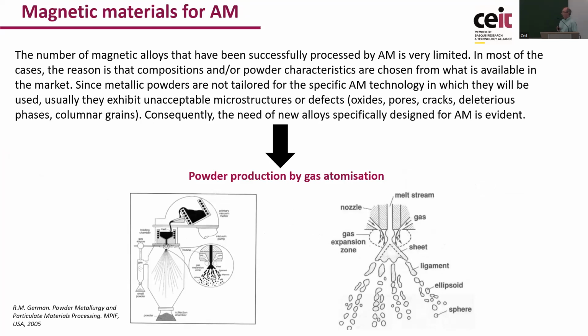The materials are going to be processed by selective laser melting in this project. The characteristics of the powders used in this additive manufacturing technology basically are that they must be spherical to have a good flowability and form a bed with uniform density. The typical particle size range is between 20 and 63 microns. And if possible, they must have a low oxygen content. So gas atomization is a very suitable process to produce this kind of powders.